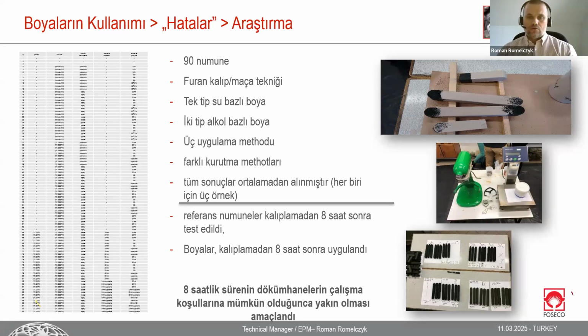Sorry, excuse me. So we talk about the Furan process. More than 100 strength bars were prepared, and 90 of them were used. As you can see, all the samples were taken 8 hours after molding. So it means that the samples were prepared over time especially for this usage.